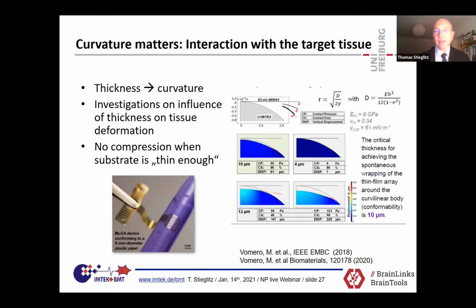which interacts with the brain. And if you have a very thin material here and you put it to the brain, during implantation, adhesion force, just by capillary forces, just bends it on the brain without anything. If you get thicker, 10 microns instead of 4, you have a small interaction. The thicker you get, the more pressure you apply on the brain when trying to make it conformable. This was something that we tried out and found out that we were lucky, because incidentally, we always had the right thickness of our material, that we stay in that really good range, that we do not apply any force or any significant force on the surface of the brain.